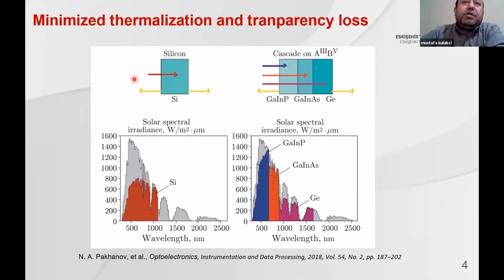So when you look here, over silicon in single junction there is a huge amount of thermalization loss, and also a huge amount of transparency loss. But in a cascade structure, you can filter the absorbed light over different solar cell junctions from high band gap to low band gap. Here is the well-known 3-junction solar cell developed over germanium. You decrease thermalization loss as much as possible, and you also decrease transparency loss by using germanium. By increasing the number of cascade layers toward high band gap, you can decrease thermalization loss much more, or by changing the low band gap material somewhere here, you also decrease the transparency loss, so you can utilize solar radiation in a much better way.